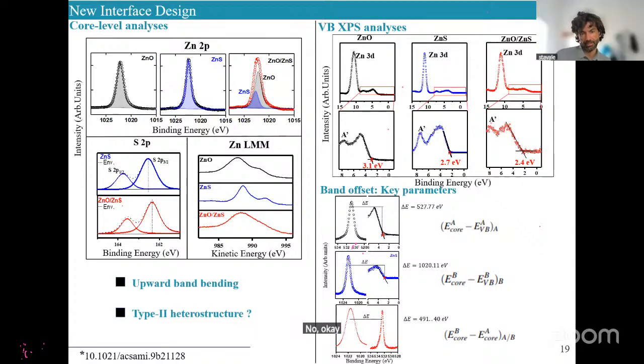Okay, I see. Maybe we don't have a good fingerprint for the shape of the Auger peak as we have for the modeling of core level peaks. But it doesn't matter if it's hybrid, whether it's a component A and B or a mix. If it's not a ternary compound, with zinc, oxygen and sulfur together, it's a linear combination of the two spectra. Most likely, yes. Otherwise, as you discussed with Tulio, the core level peaks are at the same distance when you did all these things, right? Because it's zinc in that environment. If it changes, it's no longer a linear combination, it's another compound.